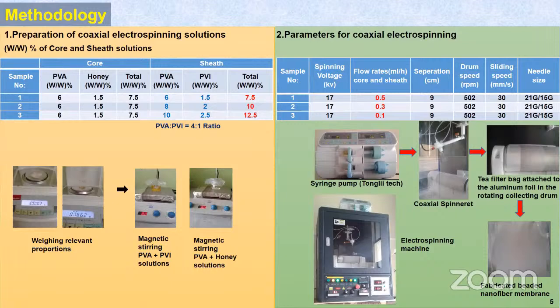For the coaxial electrospinning process, there are certain parameters we had to adjust, namely spinning voltage, flow rates, separation, drum speed, sliding speed, and the needle size. For the fabrication of 3 samples, I changed only the flow rates and kept all other parameters fixed as given in the table. Initially, we had to feed the relevant core and shell solutions, and they reach the coaxial spinneret after applying voltages and so on. We can fabricate the beaded nanofibers on tea bag and the aluminum foil simultaneously.